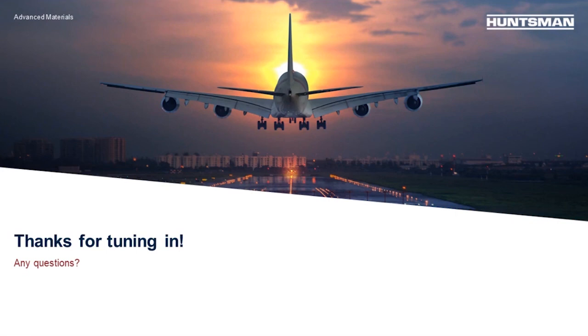Okay. What is the storage life at room temperature? Good question. Which adhesive are we looking at? It doesn't say. Okay, it's a very fair question, a good question to ask. I'll address that for all three products. For the Epibond 200, it's 1 year at room temperature, and we're calling room temperature roughly 75 degrees Fahrenheit, but it could be as high as 104 degrees Fahrenheit. So 1 year for it.